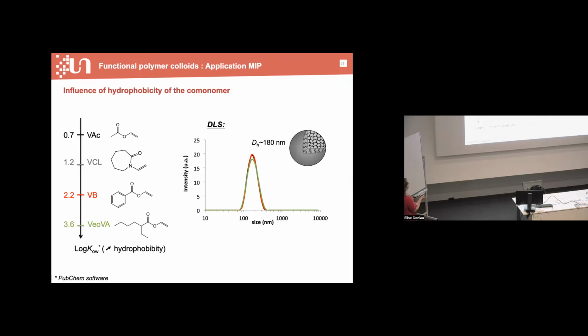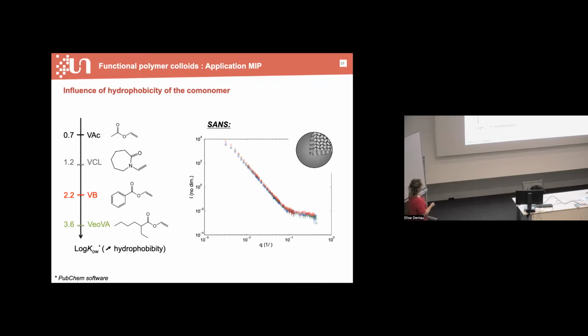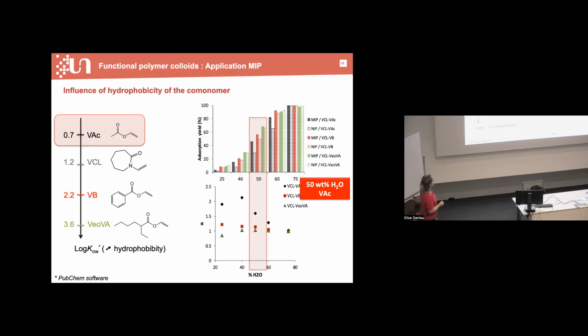Then, in order to increase the adsorption yield, we thought that we could vary the hydrophobicity of the comonomer, and we selected 3 different comonomers with a different octanol in water partition coefficient. First, we characterized the microgel by DLS, and we can see that the size was not influenced by the hydrophobicity of the monomer. And the inner structure, which could be characterized by neutron scattering, is also exactly the same, as the curves exactly overlay here in this graph. And then we found that the best comonomer is the vinyl acetate, and it is the less hydrophobic because it allows the specific recognition using the interaction with the vinyl caprolactam.